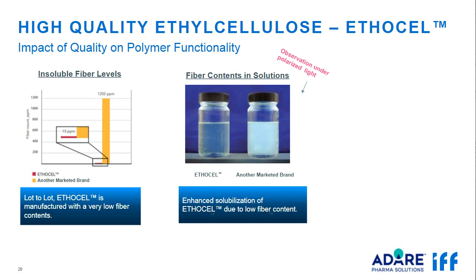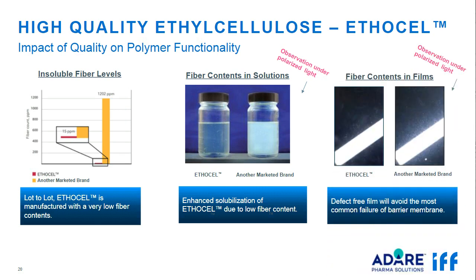The respective films from each solution are shown here. The other brand of cellulose scatters more light as compared to Ethocel film, indicating imperfection and defects. A defect-free film will avoid the most common failure in barrier membrane coating, like film ruptures and dose dumping, as mentioned.